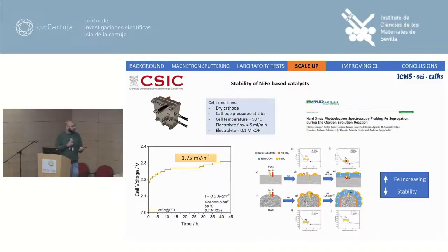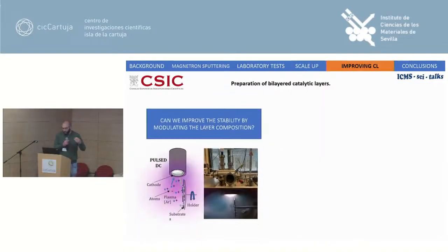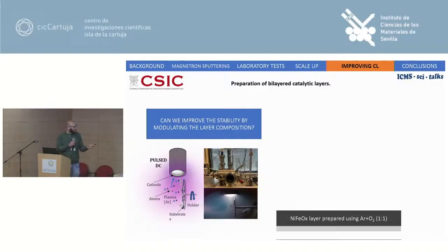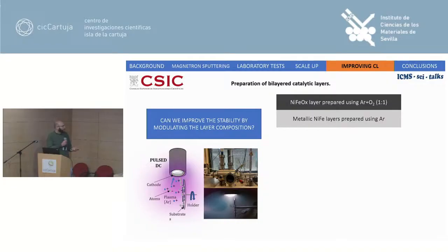So with different studies, we determined that one of the causes that promote this degradation is the oxidation of the electrode for the oxygen, the anode. When it's working in oxygen evolution reaction condition, it suffers an oxidation that promotes the segregation of iron, and we determined that probably the increase in the iron amount during the working conditions promotes the deactivation of the catalyst. So here we thought about an alternative to solve this problem for the anode, and we developed a bilayer catalyst coating, which is the original title of this presentation, by the modification of the magnetron sputtering conditions.